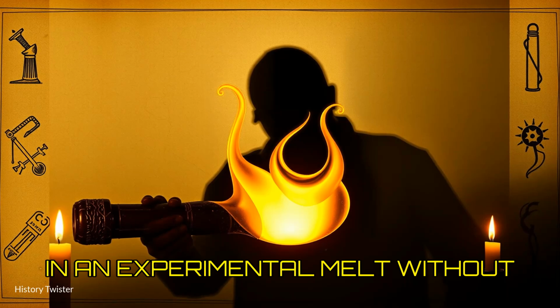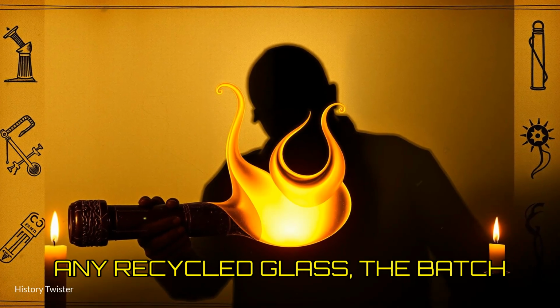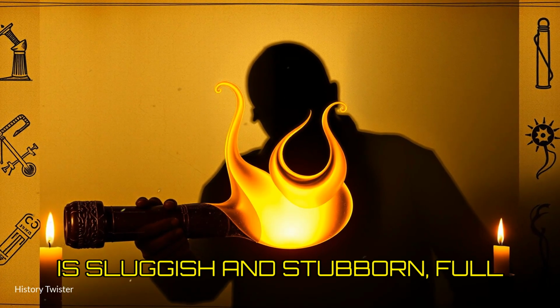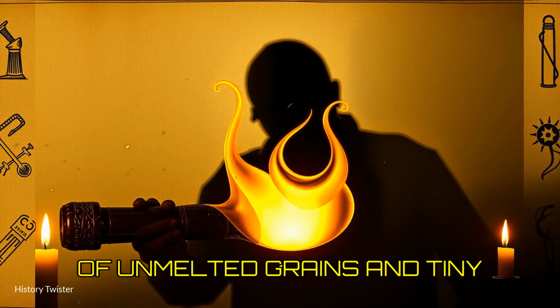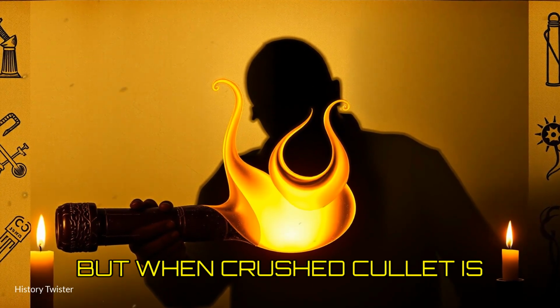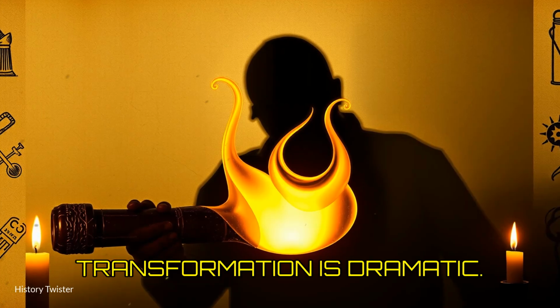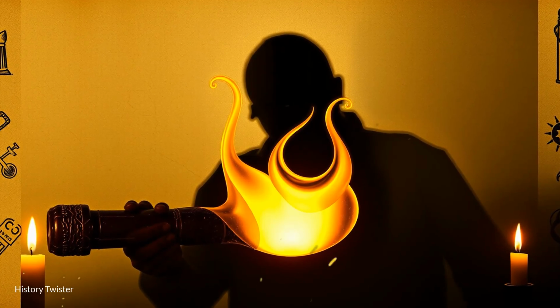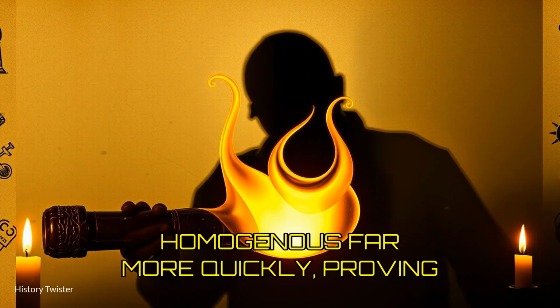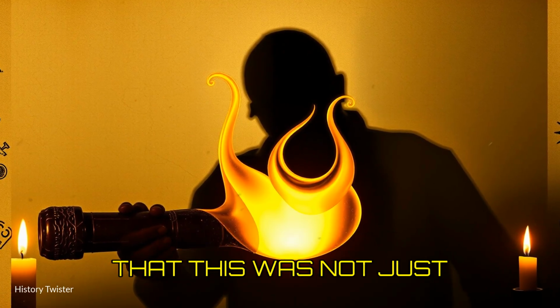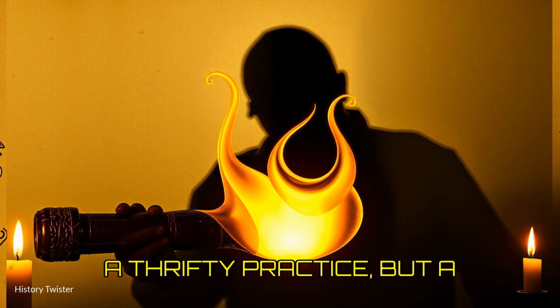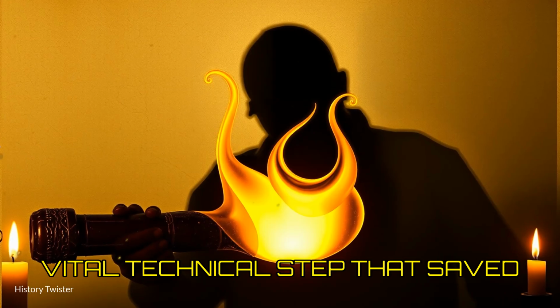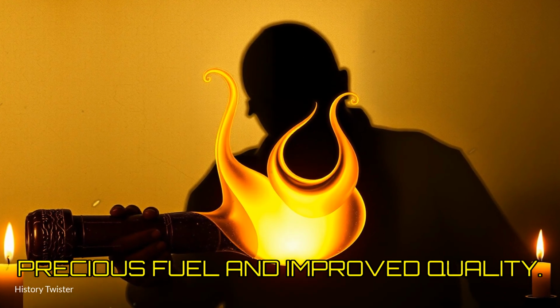In an experimental melt without any recycled glass, the batch is sluggish and stubborn, full of unmelted grains and tiny bubbles. But when crushed cullet is added to the mix, the transformation is dramatic. The melt becomes fluid and homogeneous far more quickly, proving that this was not just a thrifty practice, but a vital technical step that saved precious fuel and improved quality.